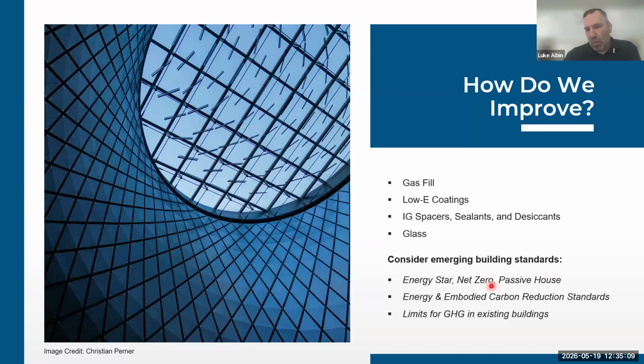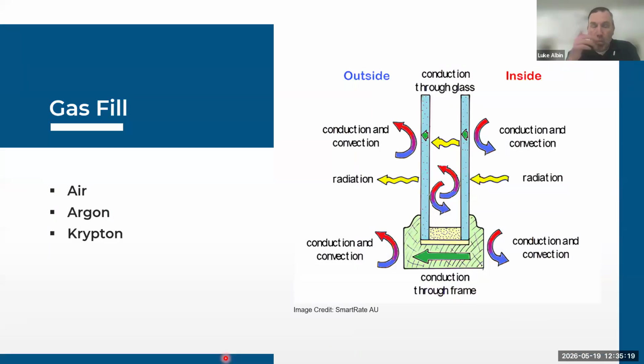But there's a couple of other things that we can do over and above adding the triple pane as well. We talk about gas fill, which was referenced in one of the previous slides. As I mentioned before, from a convection standpoint, we're trying to slow down the heat transfer, and we do that by using gases that are more dense than air. We started off with air. We are now on argon as the standard. Argon is very cheap. It represents about 1% of the atmosphere, so it's very readily available, easily used in manufacturing.